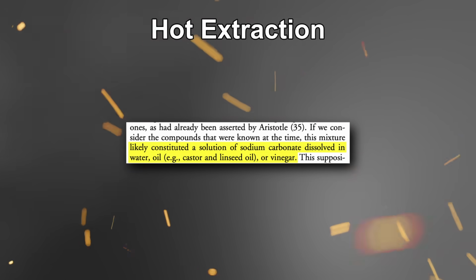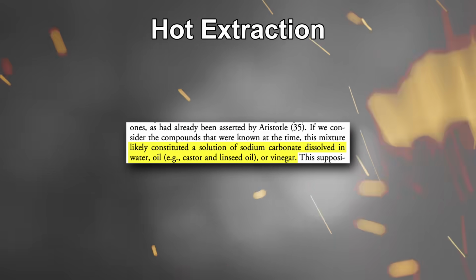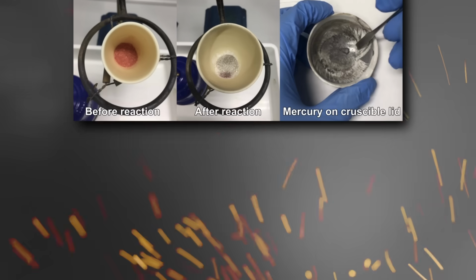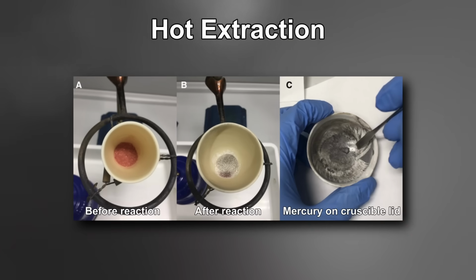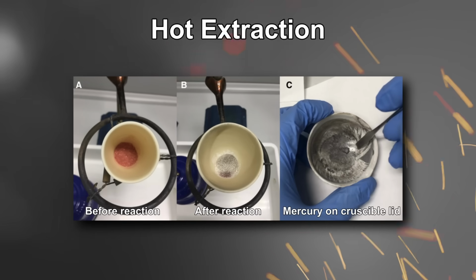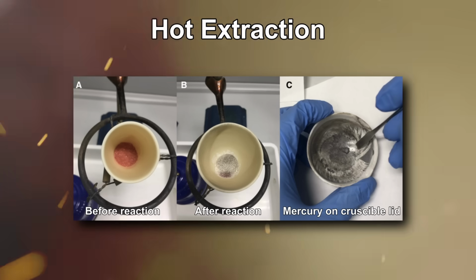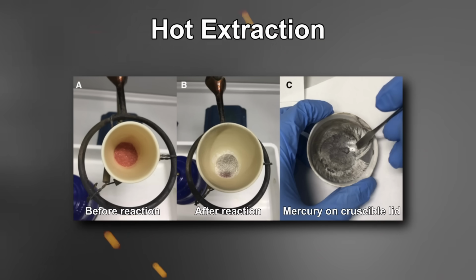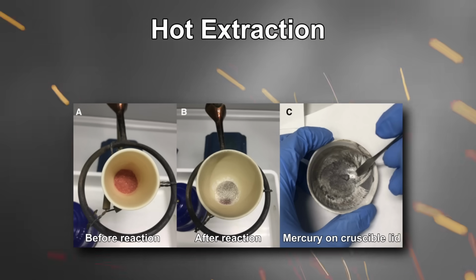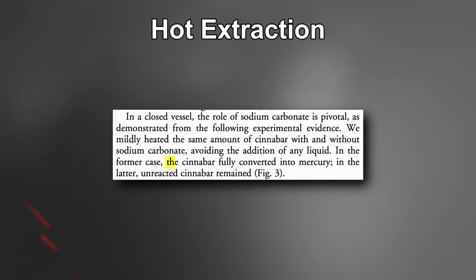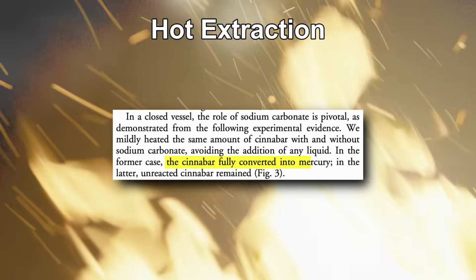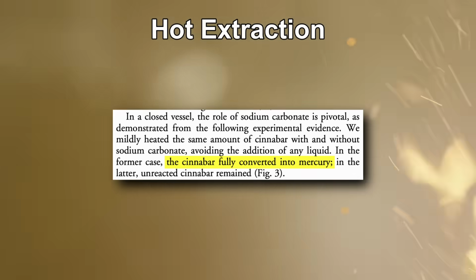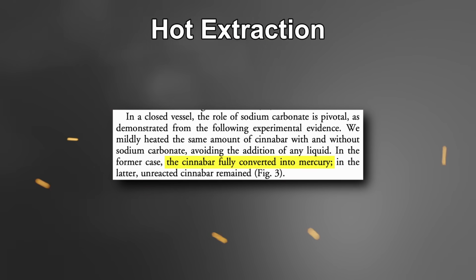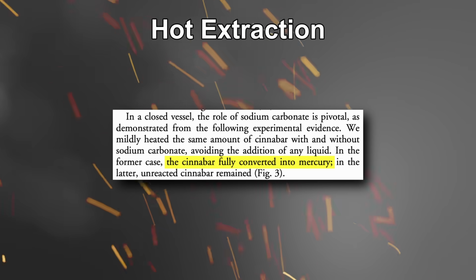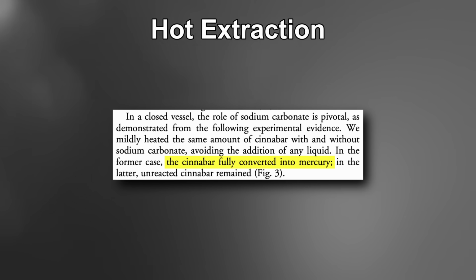Their next step was to investigate the effect of sodium carbonate, and they found that the addition of solid sodium carbonate without any liquid vastly improved the first hot extraction method, which, remember, had led to an incomplete reaction. With the addition of sodium carbonate, the cinnabar fully converted into mercury. So sodium carbonate seems to be a very effective reagent for the production of mercury. Now to test it in a liquid form.